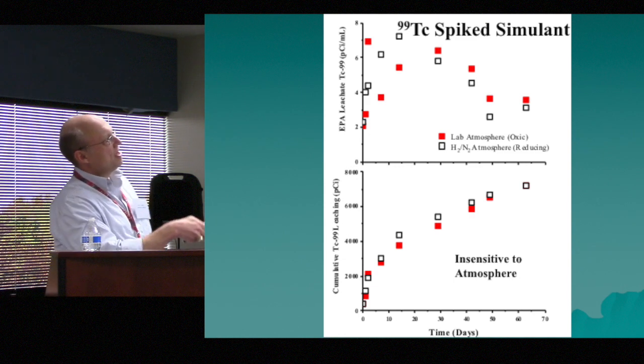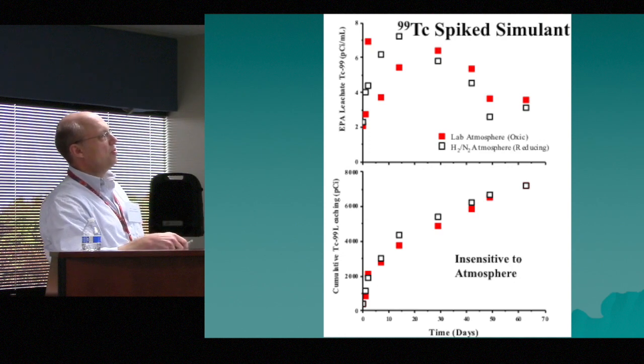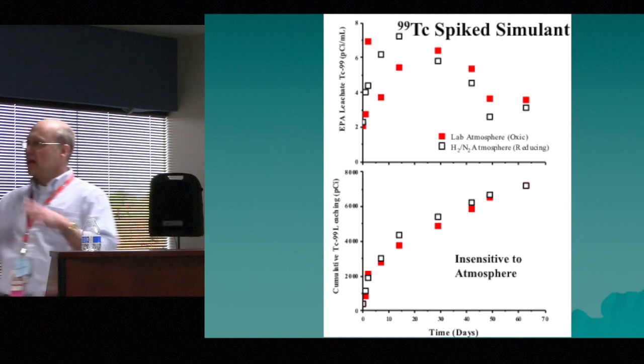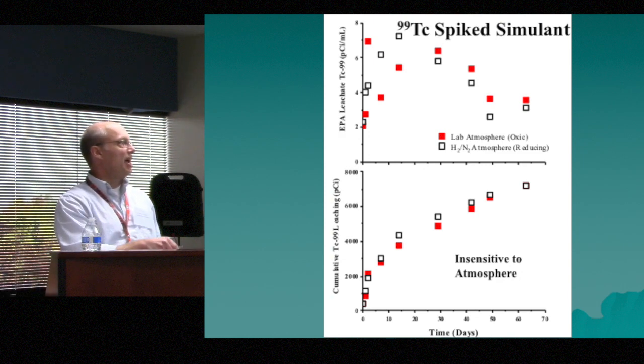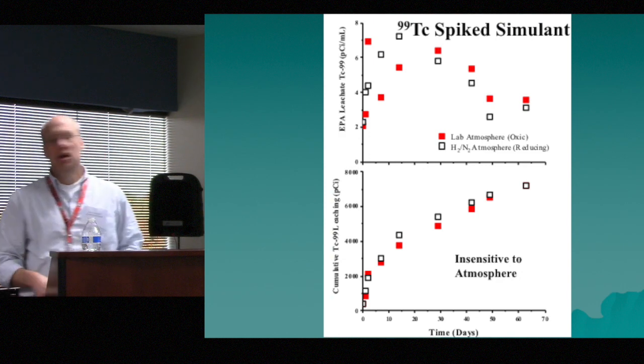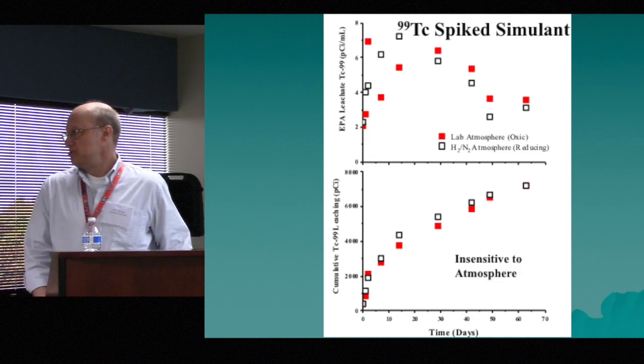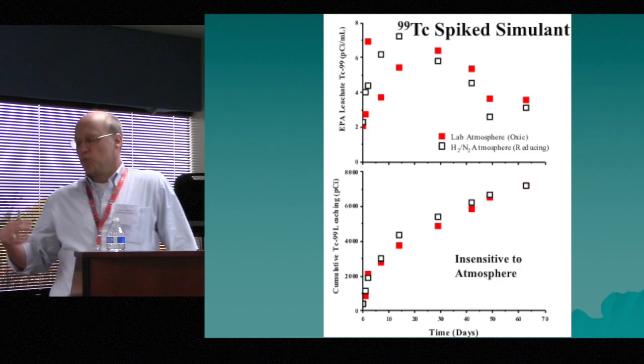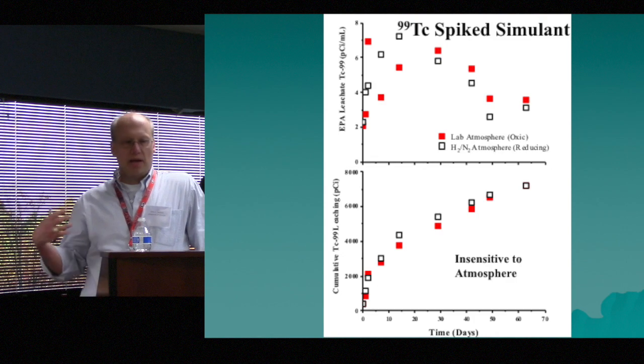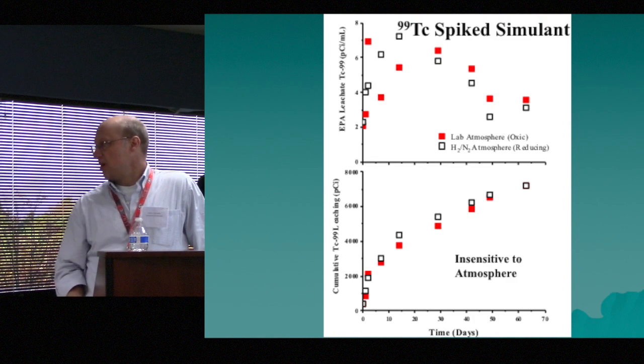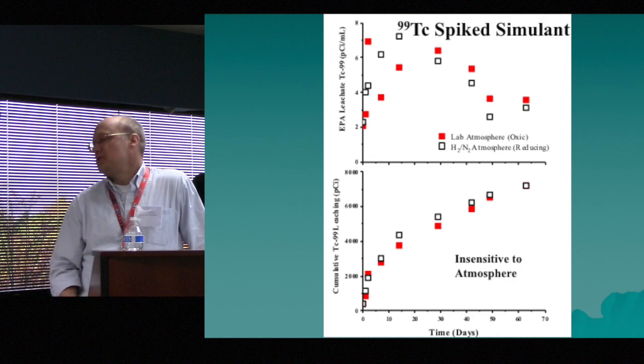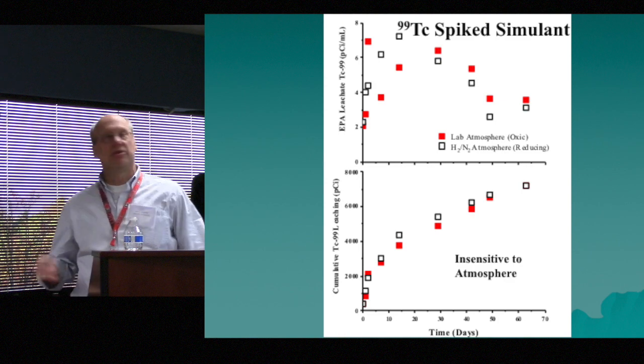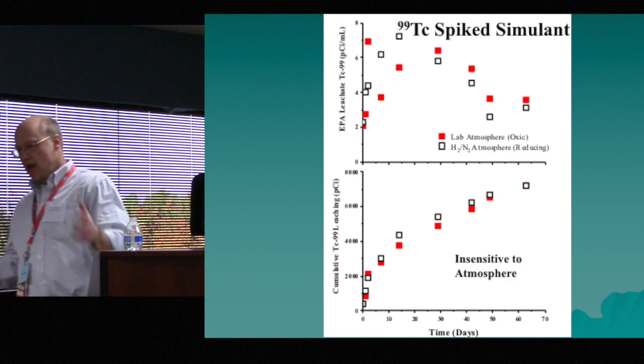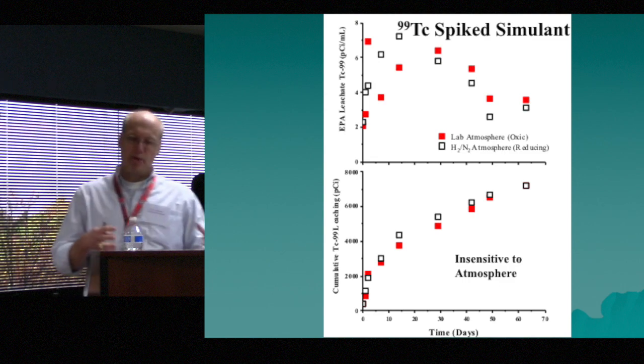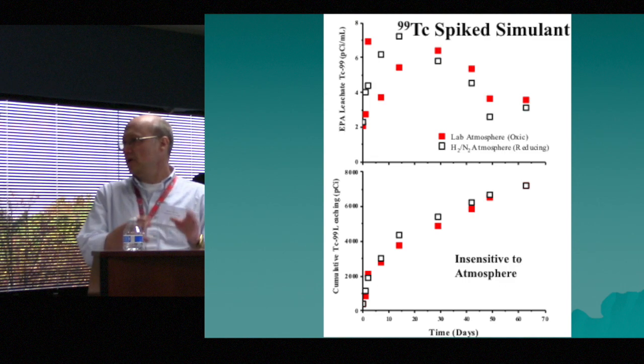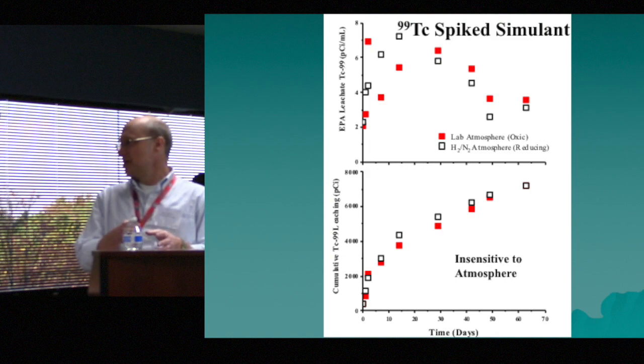And what you find is that, sure, there's a little bit of differences between the 2 in the various samples, but when you start looking at the actual cumulative amount, it was completely insensitive to atmosphere. And this is directly opposite of what you see when you grind material up. So this just suggests that even though we're trying to expose it to the atmosphere that it might be exposed to, inside the material, it's still controlling its own chemistry.